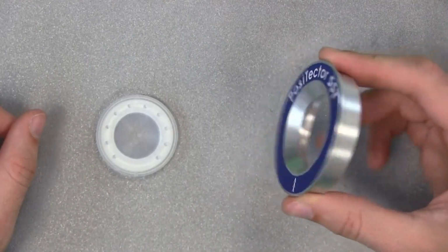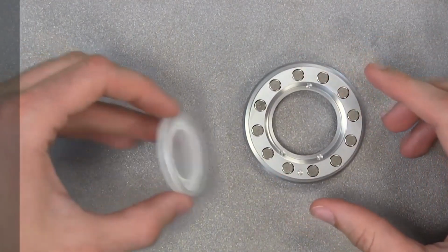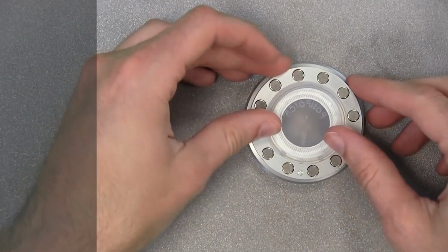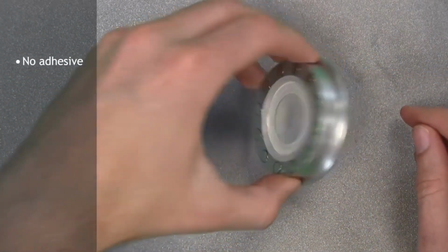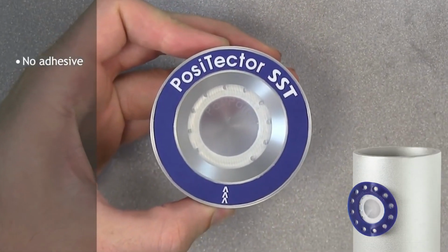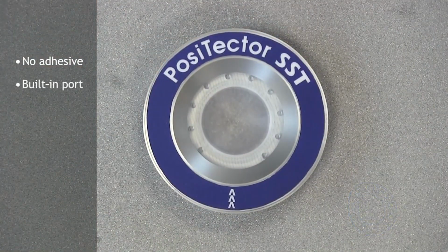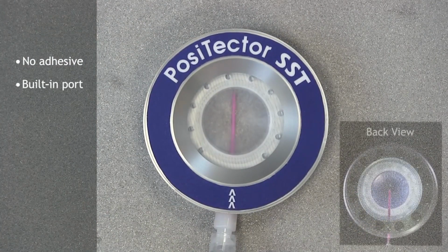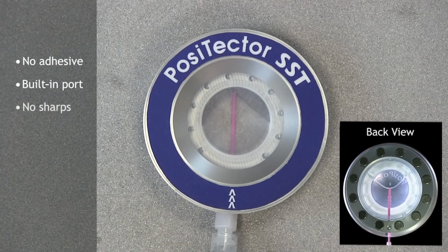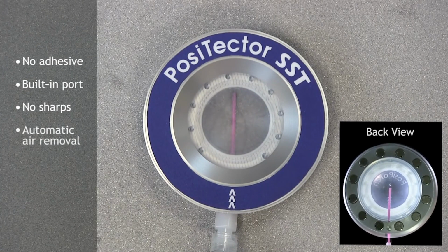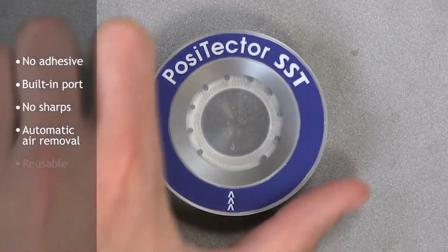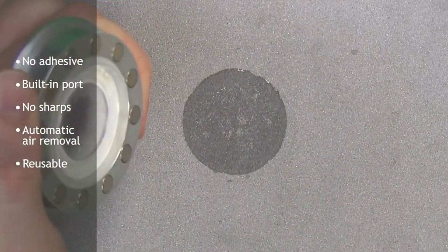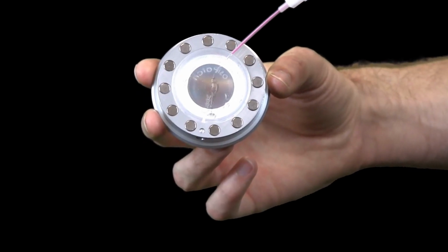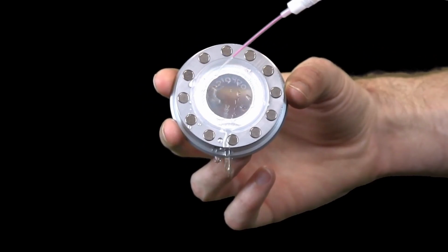The revolutionary DeFelsko PosiPatch further simplifies the Bresle method. It is functionally equivalent to traditional Bresle patches, but requires no adhesive as it is held against the surface by a rigid or flexible magnetic holding ring. It has a built-in port which allows fluid to be injected using a dull polypropylene dispensing tube, eliminating sharp needles from the test. It features a patented air-permeable membrane, which automatically releases trapped air as water is injected, then agitates the water as it is withdrawn. It is also reusable, and a single PosiPatch can be used repeatedly until worn. Just rinse the test chamber with deionized water between uses.